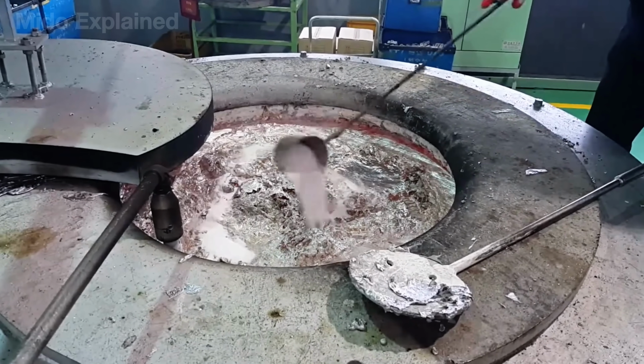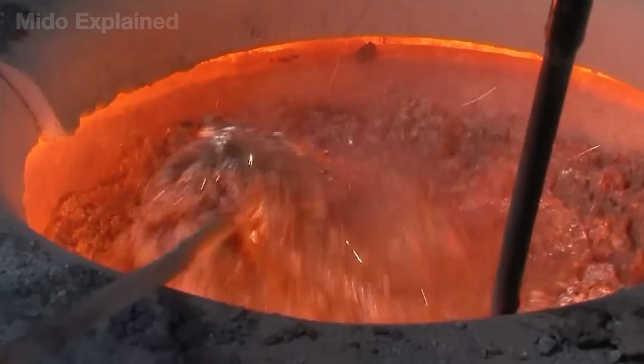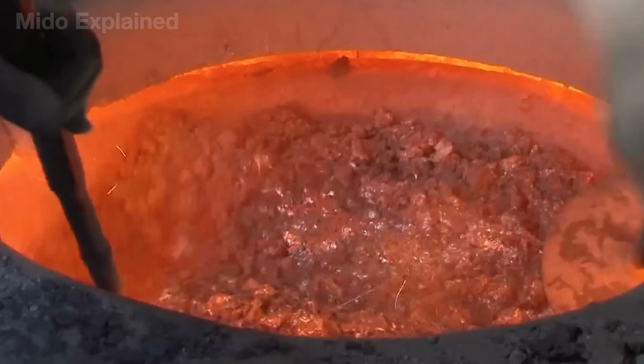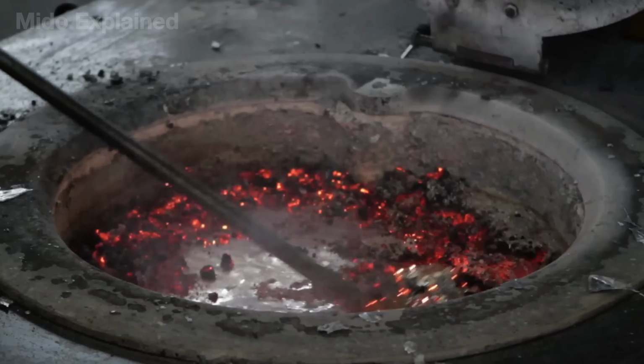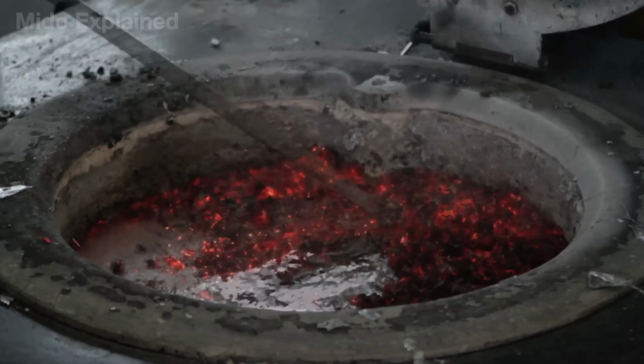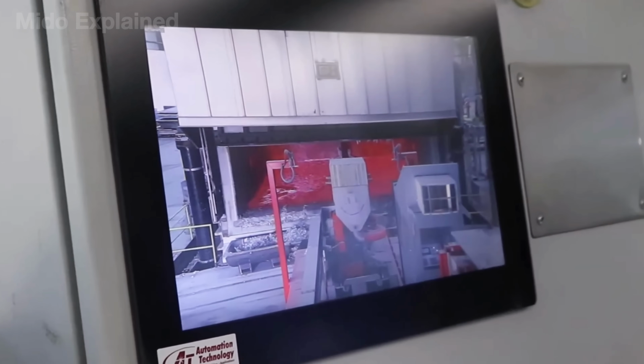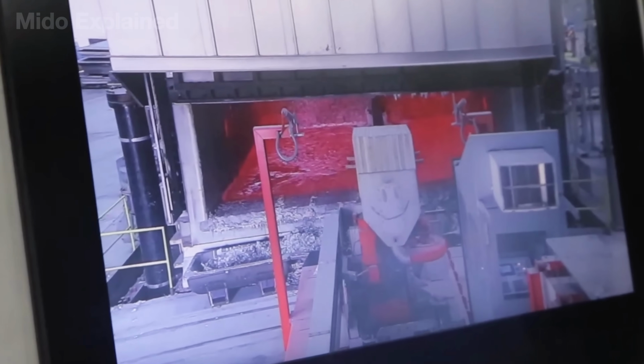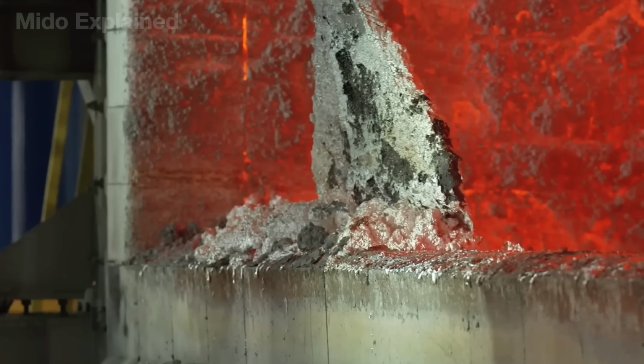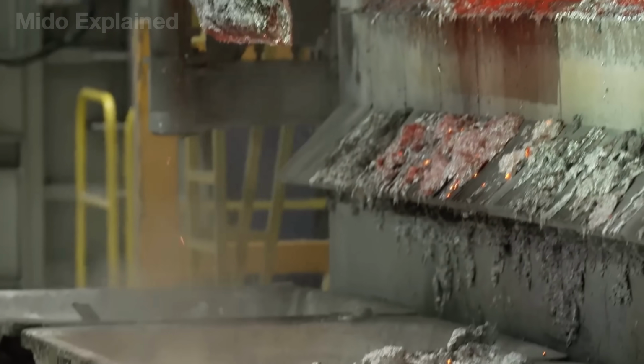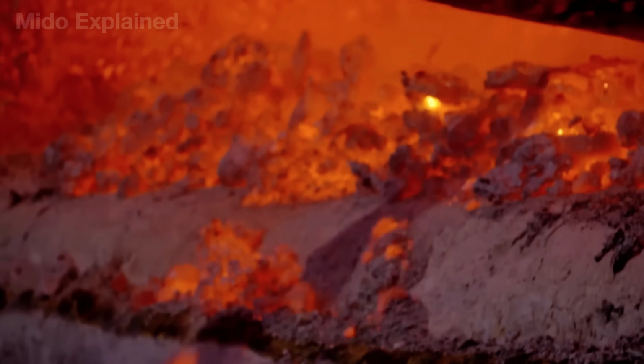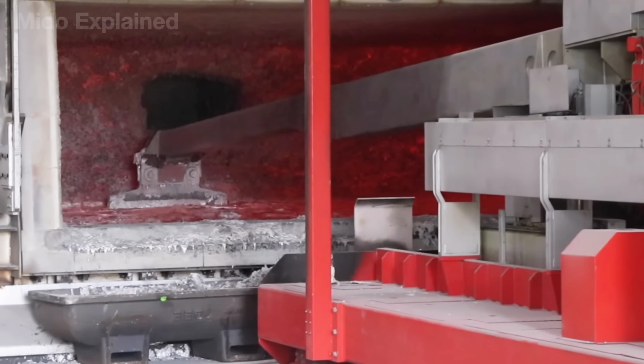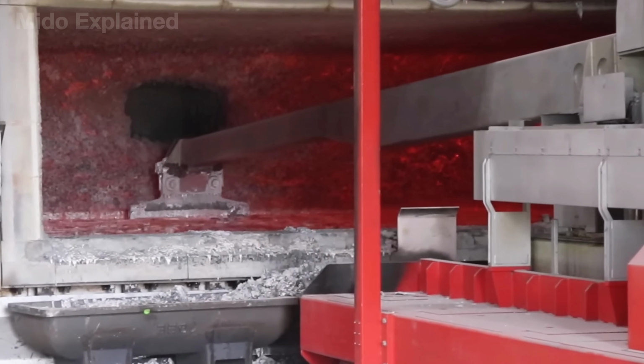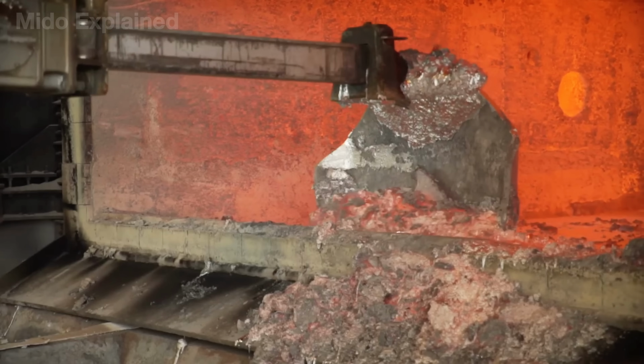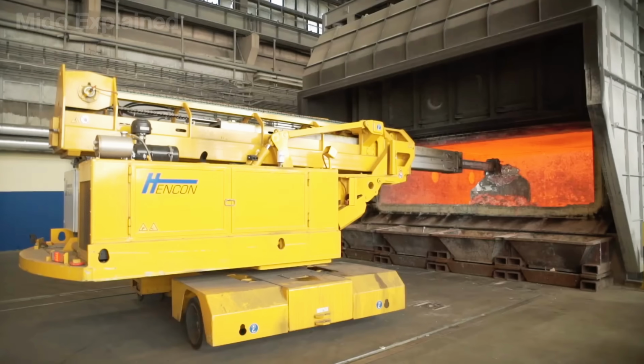When aluminum melts in a furnace, a layer of slag called dross gradually appears on the metal's surface. This slag is formed from oxidized aluminum, along with dirt, leftover paint residue, and other impurities. To remove it, specialized slag scraping equipment or robotic arms gently skim off the dross floating on the surface and remove it. This process is repeated several times throughout the melting process to keep the molten aluminum clean and stable.